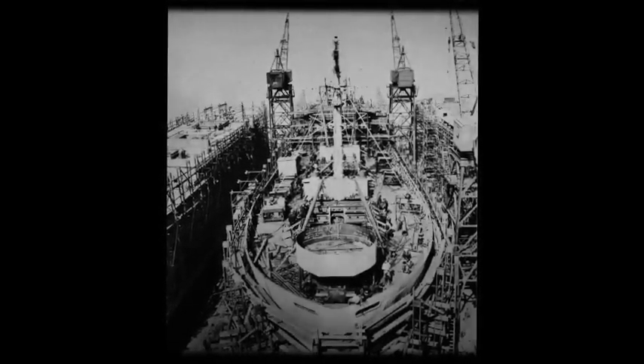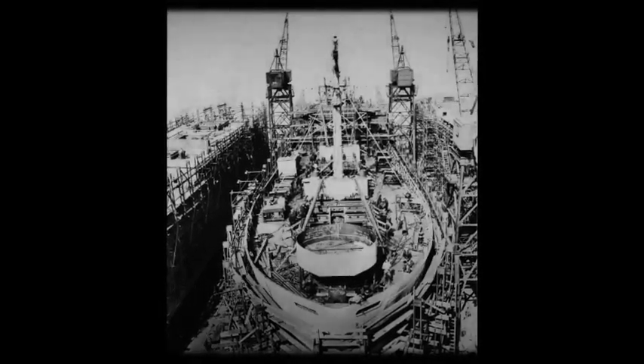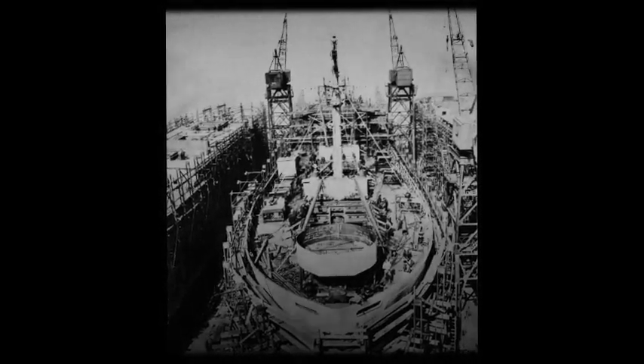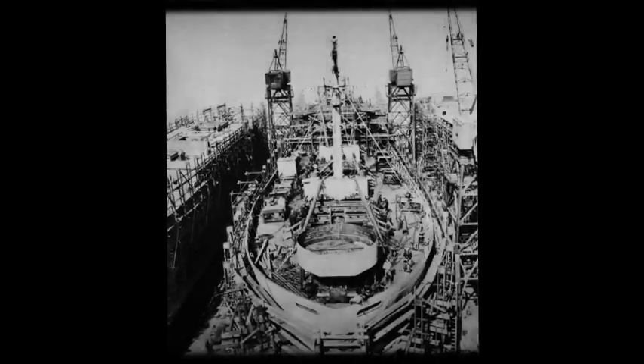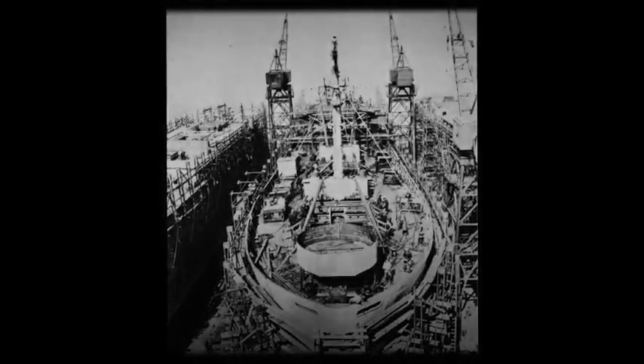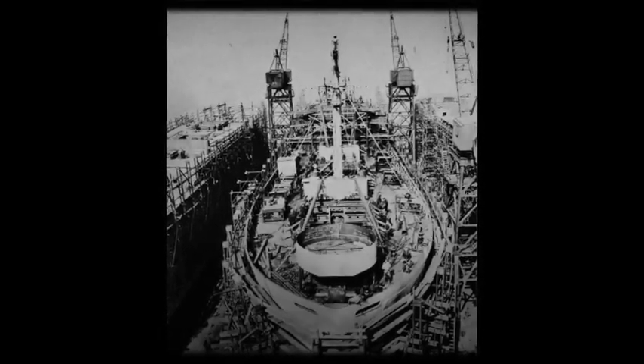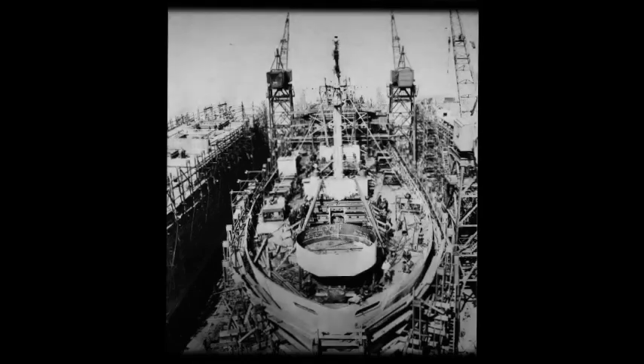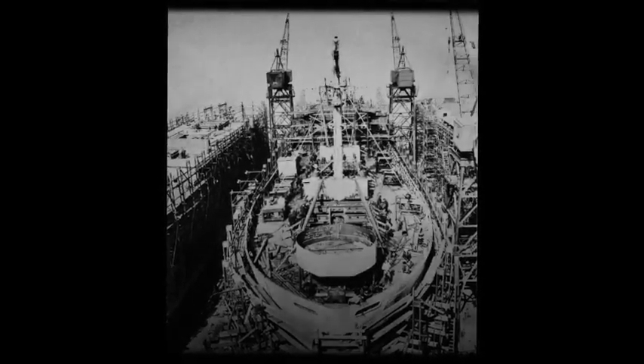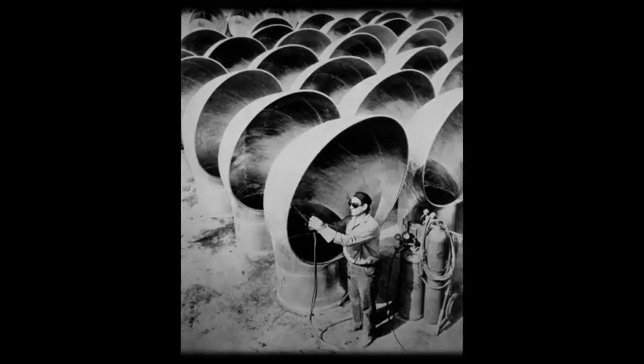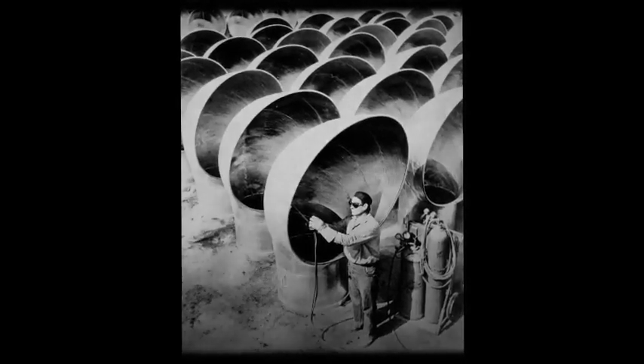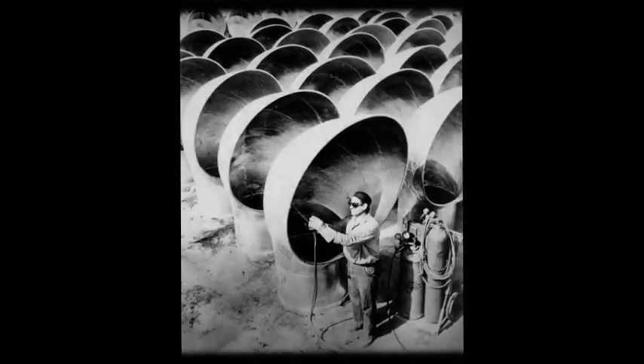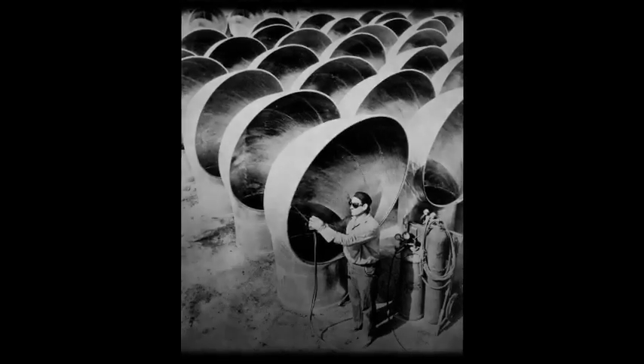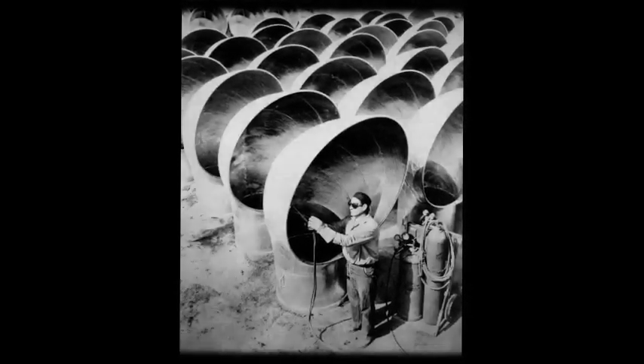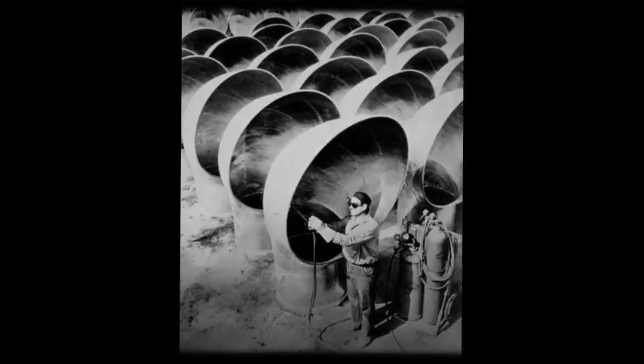The Liberty ships were being damaged by what metal experts call brittle fracture spreading. The kind of steel used in their hulls, called carbon ship steel, worked fine in warm water, but changed when it hit the freezing North Atlantic. Below about 40 degrees Fahrenheit, the steel lost its ability to bend. Normally, metal handles stress by bending a little instead of breaking. But cold steel loses that bend. It becomes stiff and fragile like glass instead of tough, like the steel the welders used back in California's mild weather. When this stiff steel met trapped stress at a sharp spot like the square edge of a cargo hatch, the laws of physics took over fast.